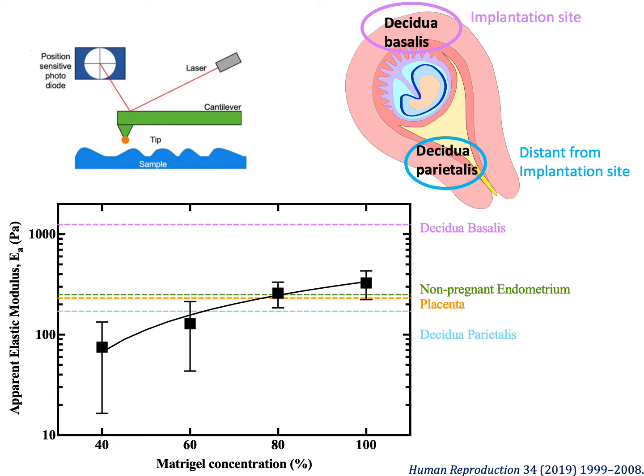This is a graph showing those results in summary, and the black curve there is for Matrigel, the hydrogel that we were using in the microfluidic device. As you can see, depending on the concentration of the Matrigel, going from 40% to 100% as reconstituted according to the manufacturer, the stiffness of the Matrigel is reasonably comparable to the non-pregnant endometrium, to the placenta, or to the decidua parietalis distant from the implantation site, but significantly less stiff than the decidua basalis where the implantation site has occurred. So in fact, this may not be the best case scenario in terms of understanding these interactions between the trophoblast cells and this artificial extracellular matrix, and this calls for some potential thinking about development of a new hydrogel for this microfluidics assay.